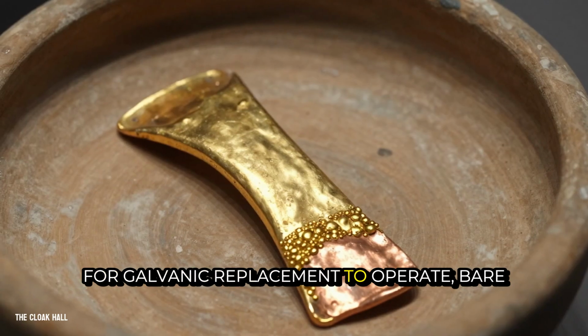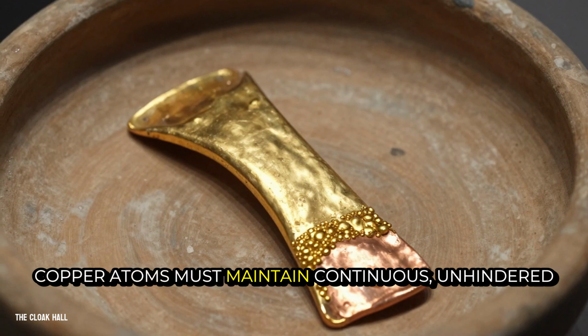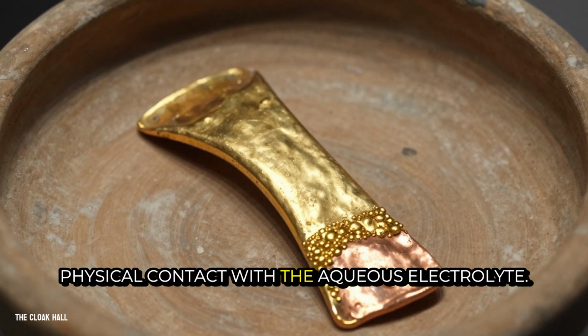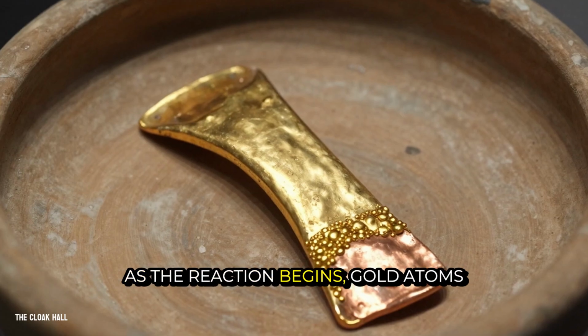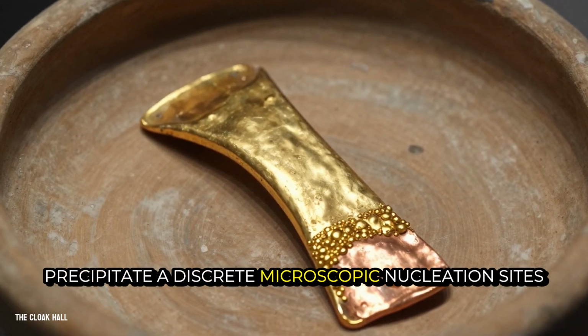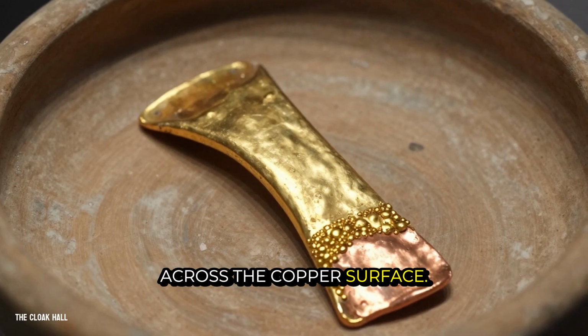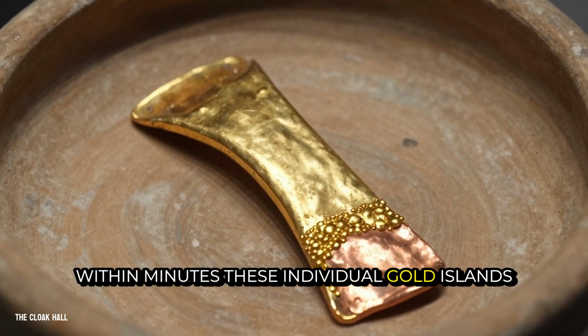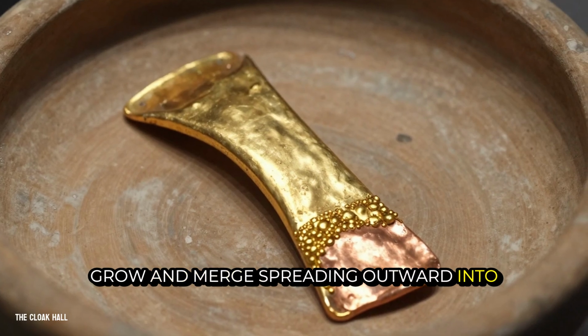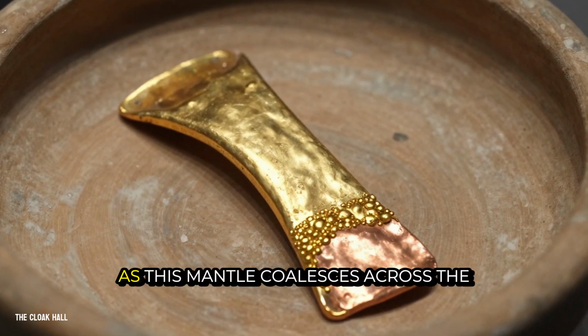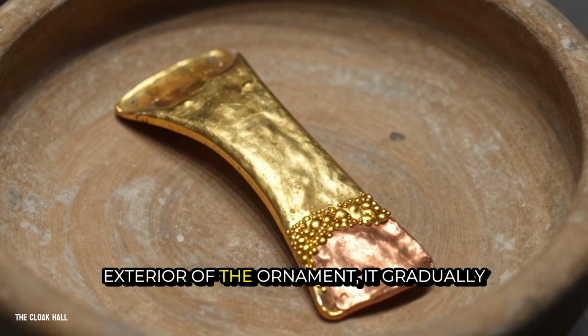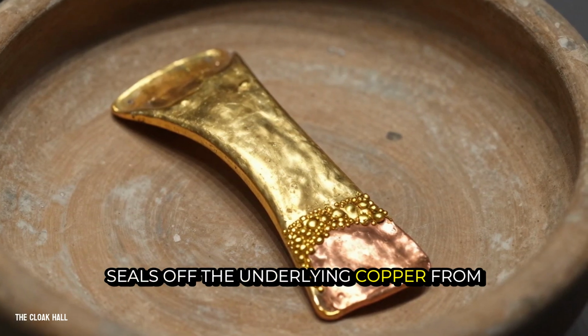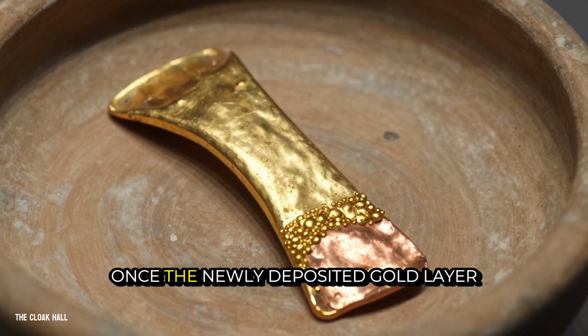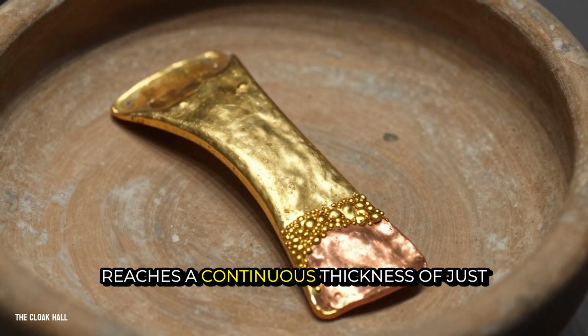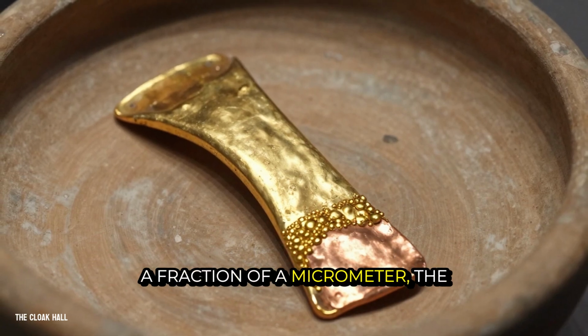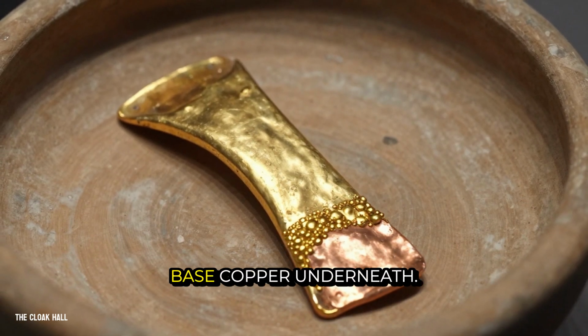For galvanic replacement to operate, bare copper atoms must maintain continuous, unhindered physical contact with the aqueous electrolyte. As the reaction begins, gold atoms precipitate at discrete microscopic nucleation sites across the copper surface. Within minutes, these individual gold islands grow and merge, spreading outward into a continuous metallic blanket. As this mantle coalesces across the exterior of the ornament, it gradually seals off the underlying copper from the surrounding liquid. Once the newly deposited gold layer reaches a continuous thickness of just a fraction of a micrometer, the electrolyte can no longer touch the base copper underneath.